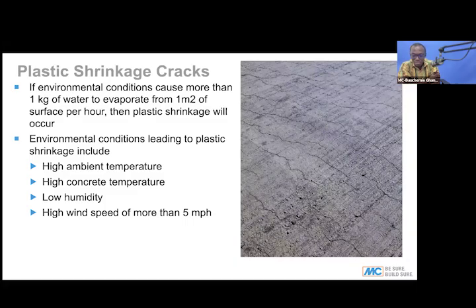Now, the environmental conditions that cause this kind of cracks start with the ambient temperature. Higher temperatures will definitely result in a higher loss of moisture. And when the concrete temperature is so high, when the concrete is hot, you also have a lot of moisture leaving the concrete. Then there is low humidity, especially if you are casting concrete in the dry season when the humidity is very, very low. In that case, the loss of water from the surface of the concrete will be higher than the rate of recharge, and that differential will cause plastic shrinkage on the surface and the subsequent cracking.